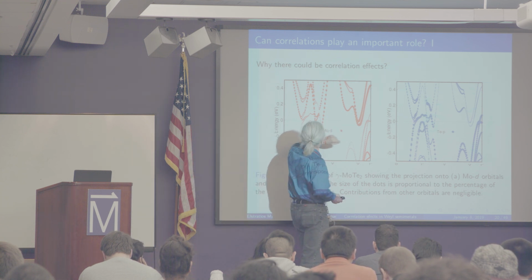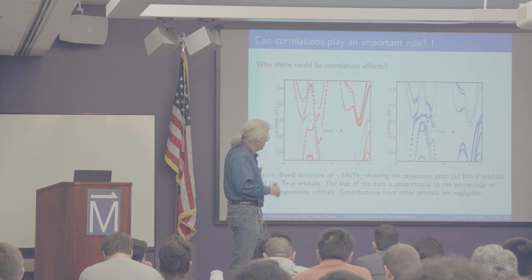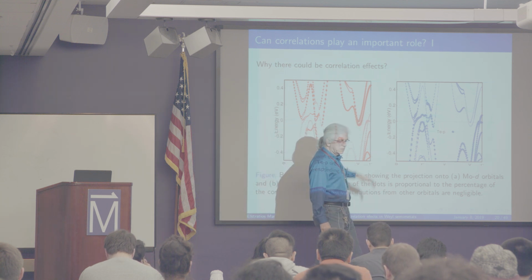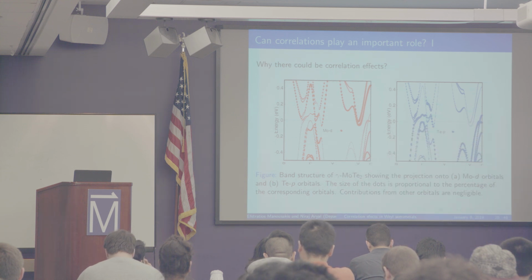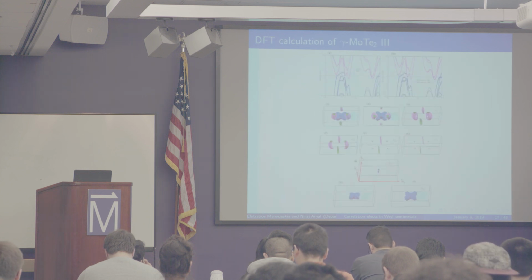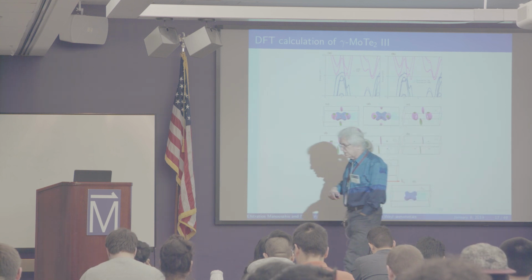And so obviously this band here, which is only like 50 meV below the Fermi level, if you put a U of the order of a couple of eV, this pushing is going to elevate this electron state upwards above the Fermi level and it might go away, because you don't want to have all this complexity. As I said, all these things here disappear right away. These pockets here, which are in DFT, disappear right away, and things become simpler.